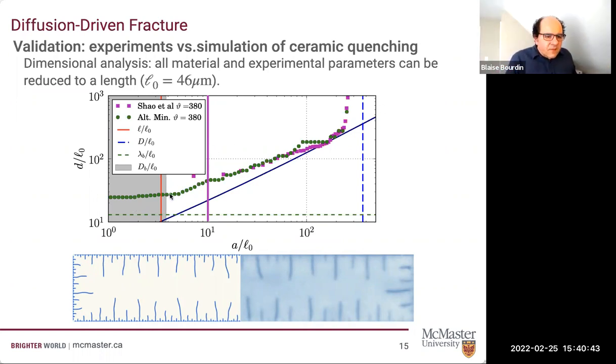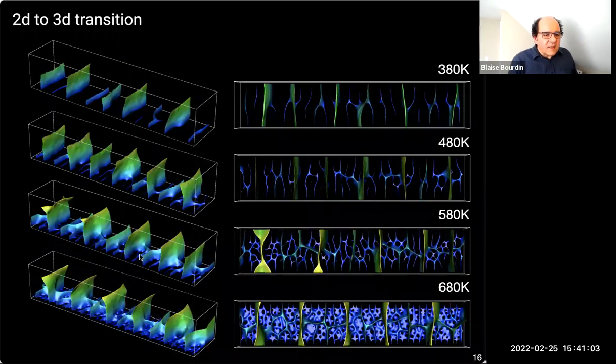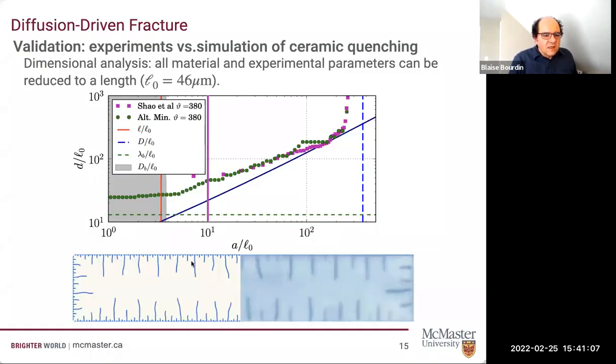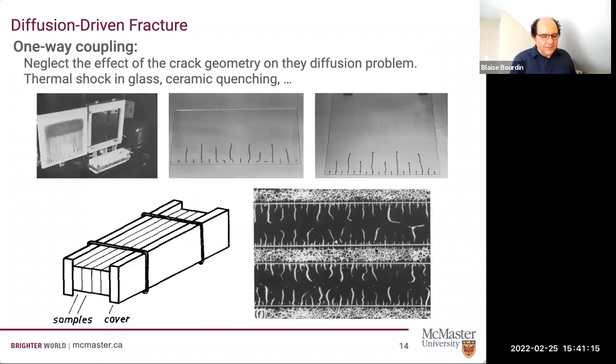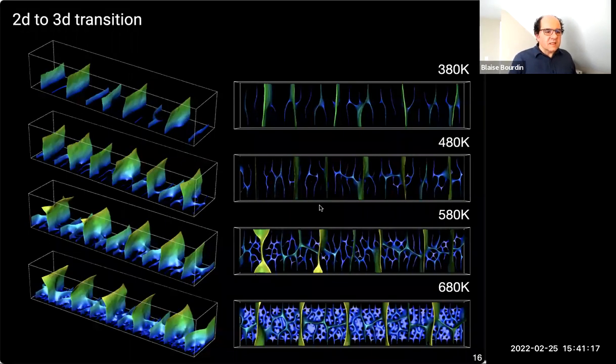To get an idea, I think at this point, we're less than 1/10 of a millimeter away from the edge. So the fact that there's no measurement is probably just a sign that there's no way to take measurements so close to that. And then what we can do is look at a closer region around this edge. Let's say I only try to simulate a piece of the edge, but do a 3D computation. And what I want to see is if I would be able to reproduce this crazing pattern here. And the answer is yes.